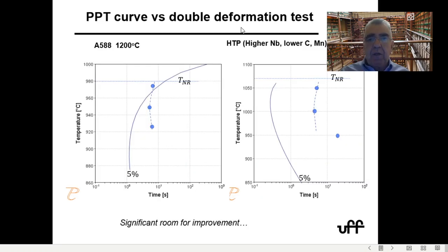So currently we have work in progress that we are relating. For instance, this is a double deformation testing, and this is the no-recrystallization temperature for this steel, which is a classical microalloy steel. And this is the 5% precipitation curve for niobium carbonitride, which is fairly reasonable maybe. And then for a higher niobium, lower carbon manganese, we have this discrepancy. But it's very interesting because we think that this is perhaps more accurate than what we were able to do in the deformation test. So we are testing this. And of course, there's significant room for improvement.